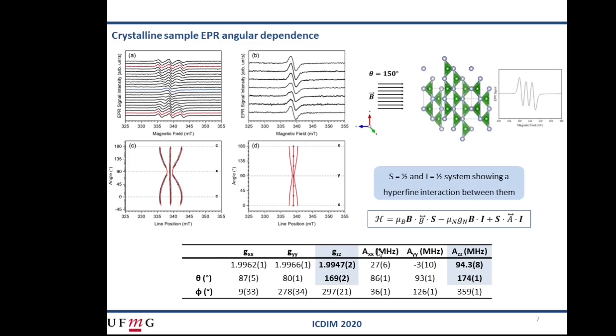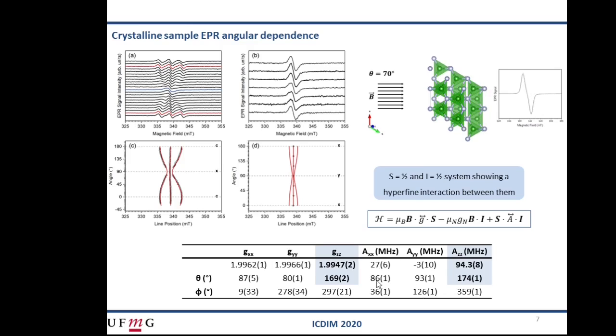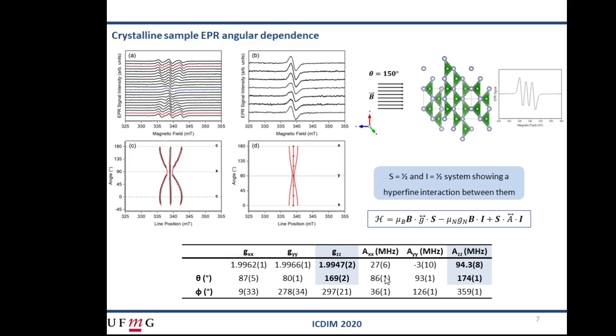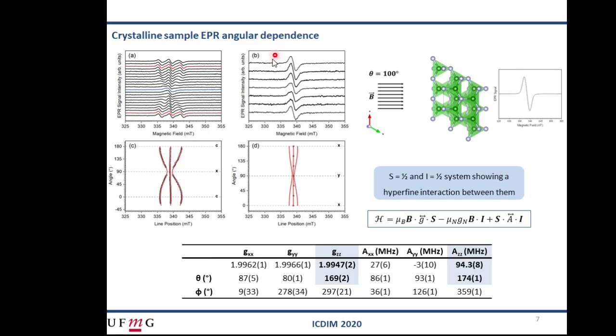In the plane of the samples, the parameters are more difficult to interpret due to the polycrystalline character of the sample. And this difficulty in interpreting them may be one of the reasons that the three EPR lines lose resolution and the final EPR spectrum exhibits this single line.